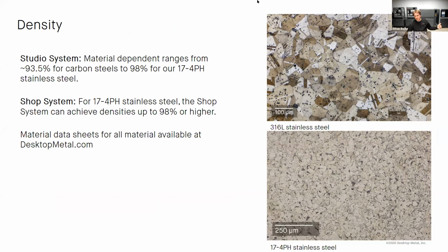When it comes to the Shop System and our binder jetting machines in 17-4 stainless steel, we're seeing densities of 98% and higher consistently, giving you those really, really high densities that you need for those end use applications, for those parts that are going to be out in the field. And again, for all the materials we have available here at Desktop Metal, you can head to our website and download those data sheets to really get a better idea of the exact properties that you can expect with these parts.